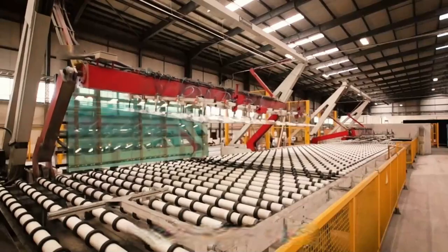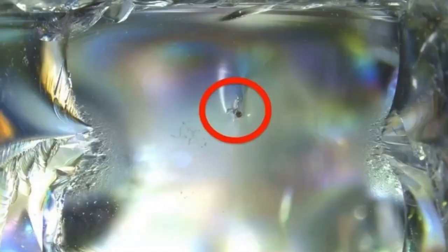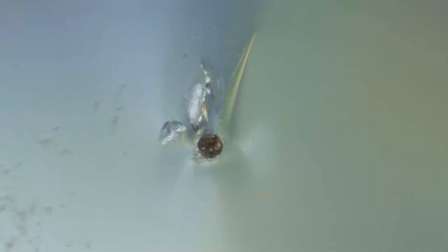If those characteristics are absent, the breakage is likely caused by external forces. The causes of tempered glass spontaneous explosion are complex and can be divided into three categories. The first is during the manufacturing process: if there are too many impurities, stones and bubbles form in the finished glass, and during rapid cooling, nickel sulfide crystals also form.